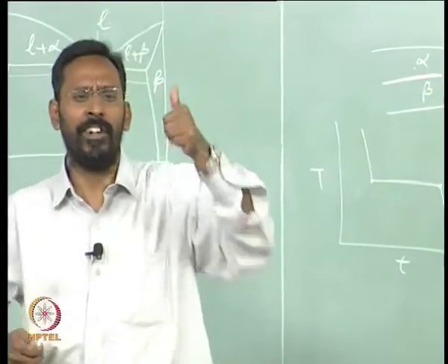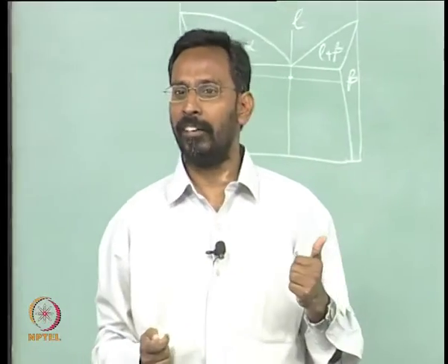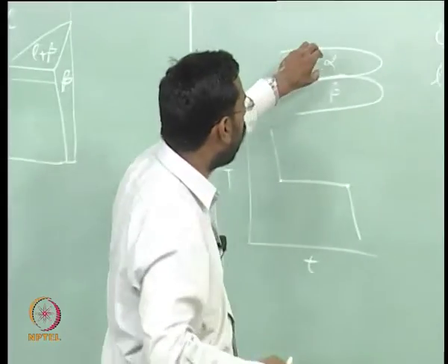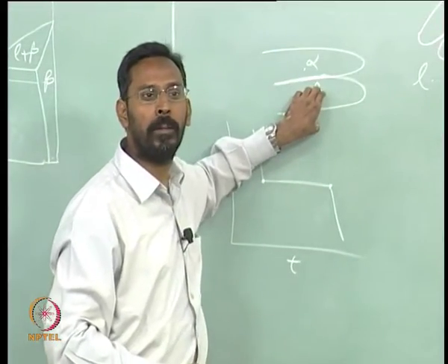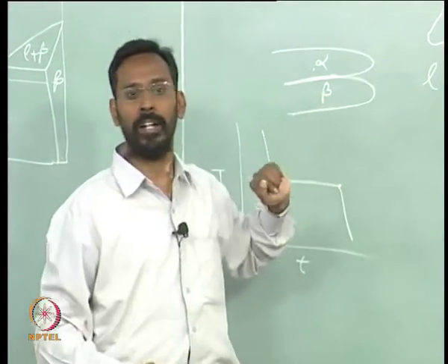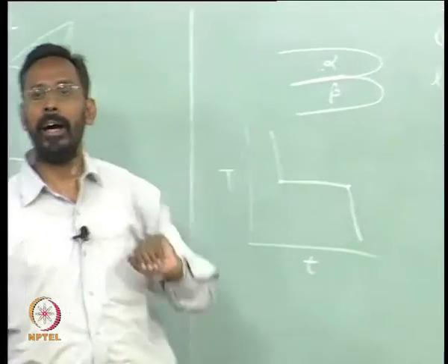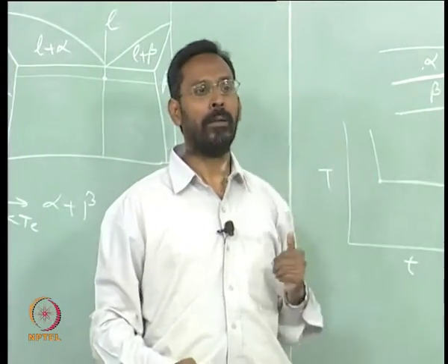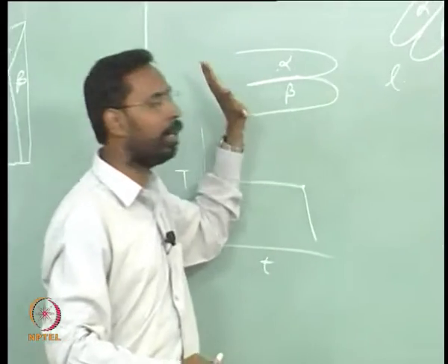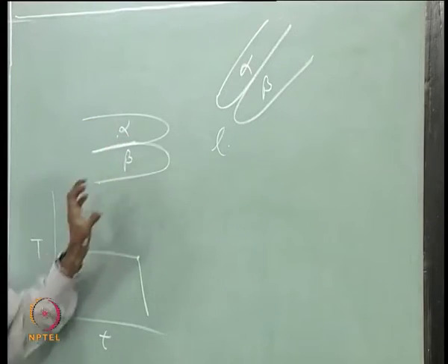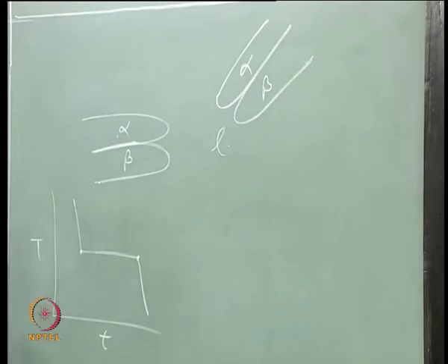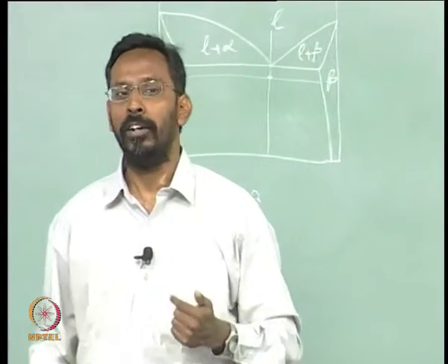It is one single liquid. One single liquid is able to supply more A atoms to alpha and more B atoms to beta. Unless you do that—if only certain atoms, let's say A atoms, are coming uniformly to both—only alpha will grow, beta will not grow, and then it will not be a coupled growth. So if you want coupled growth to happen, selective supply of atoms to alpha and beta should take place.